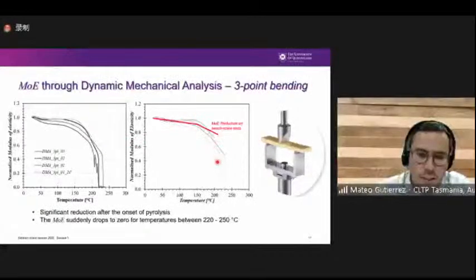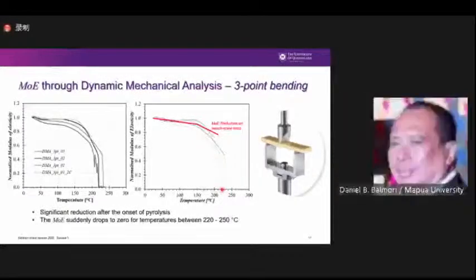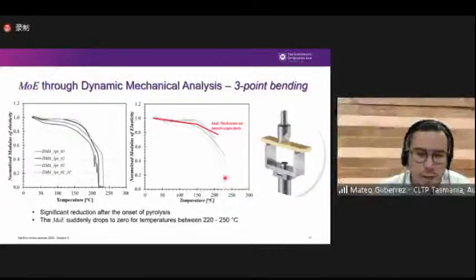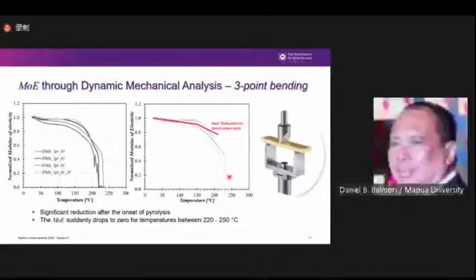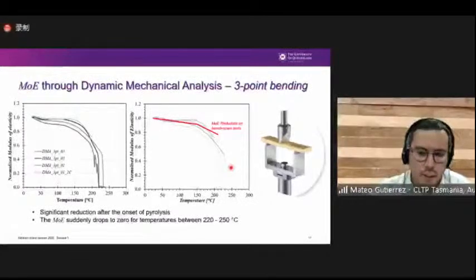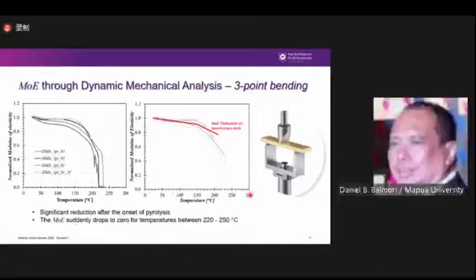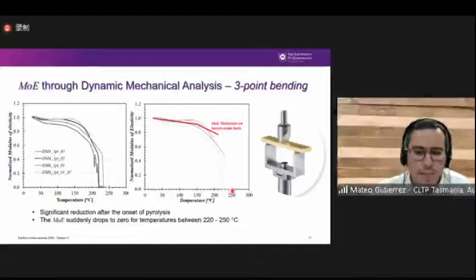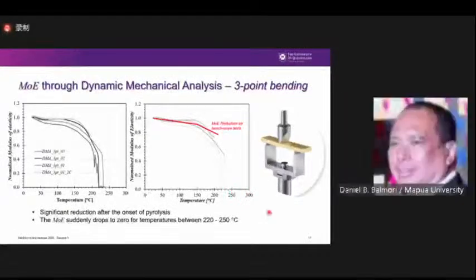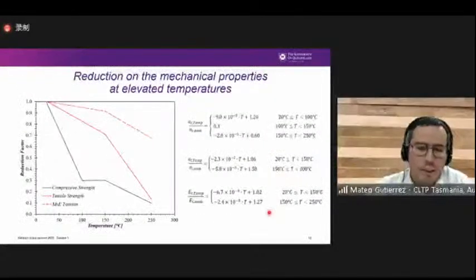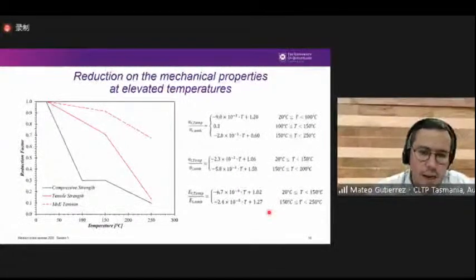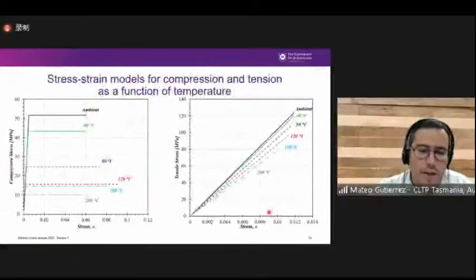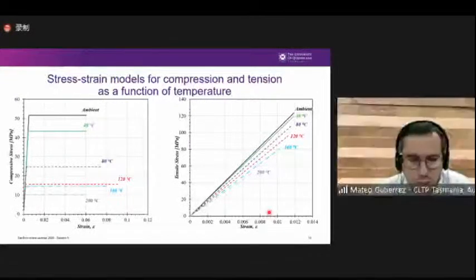And what we observe from this test is that between 220 and 250 degrees, we basically lost all the strength and stiffness of bamboo, which was a quite interesting result as well, because normally for timber, you assume that the strength is completely lost at 300 degrees, but for bamboo, it seems to be a slightly lower temperature. So basically, after we conducted all this research on the reduction of the mechanical properties, we established some equations, and then we created some constitutive models to describe the behavior of bamboo in compression and in tension at elevated temperature.